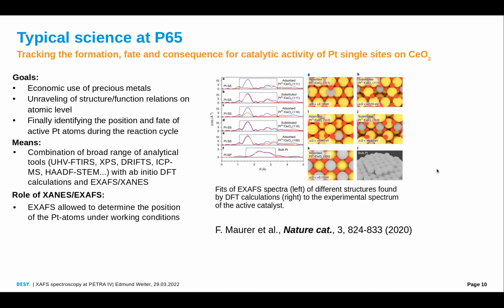Typical science is, as I said, catalysis research, and in this case, this example shows single platinum atoms on cerium dioxide, and the question was where exactly are these platinum atoms sitting? And the users, that was from Florian Maurer from Jan de Groenewald's group, they did the XAFS measurement at P65, but apart from that, they did a lot of other stuff. They did DFT calculations, for instance, came up with different models, to which they compared the experimental XAFS spectra to come up with the solution where these platinum atoms are finally sitting. So that's a very typical example.